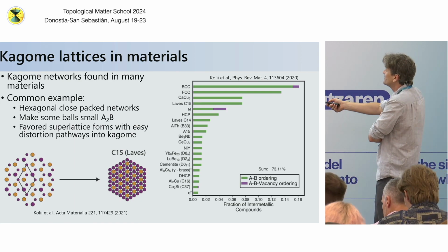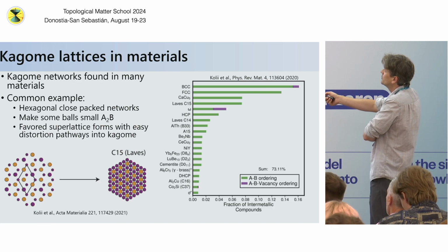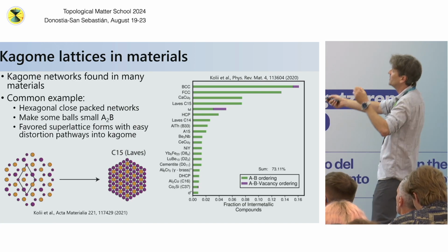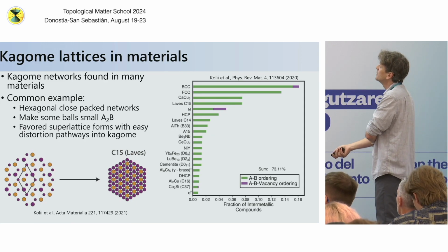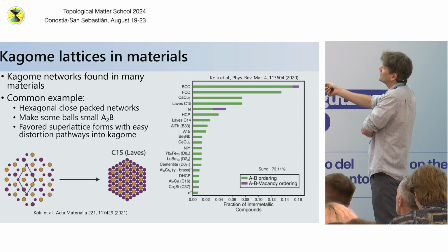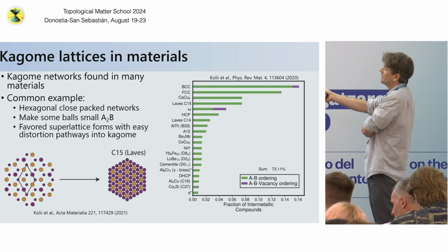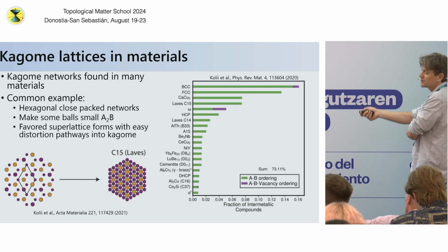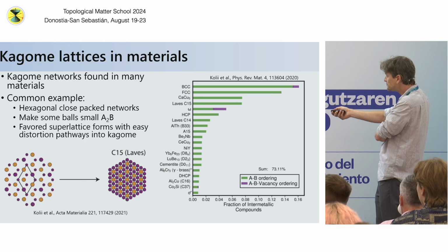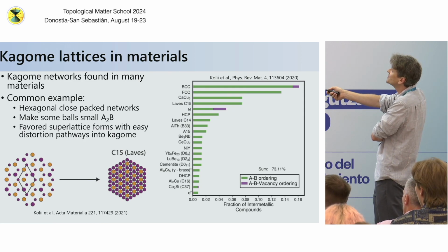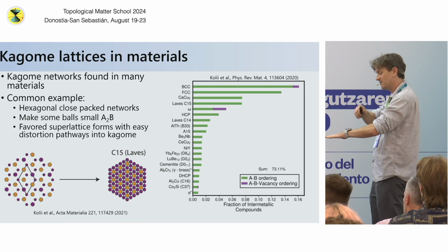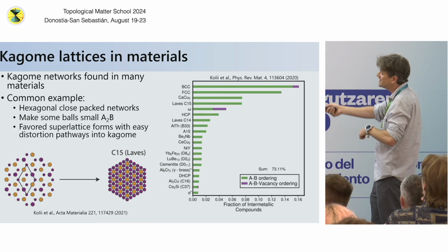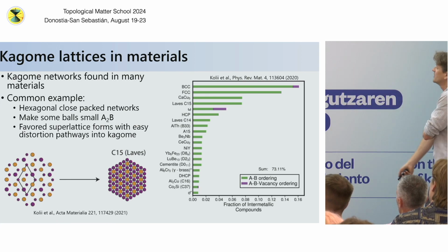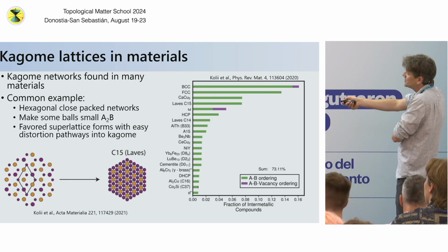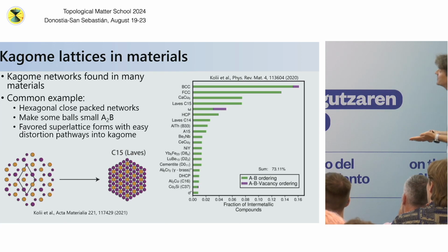And so material scientists have known this for a long time, that if you just take some network of balls, okay, let's say small balls, and you look at hexagonal close-packed networks, and then you make 2/3 of the balls small versus 1/3 large, and then you look at what kind of structures this wants to breathe into, it turns out that the favored superlattice that forms is really to distort into a Kagome lattice stacked by a triangular lattice. The details on how you phase these stackings depend on the details of the material itself, but it basically shows that the Kagome network is actually favored to form, even in this very simple model of binary intermetallics, okay?